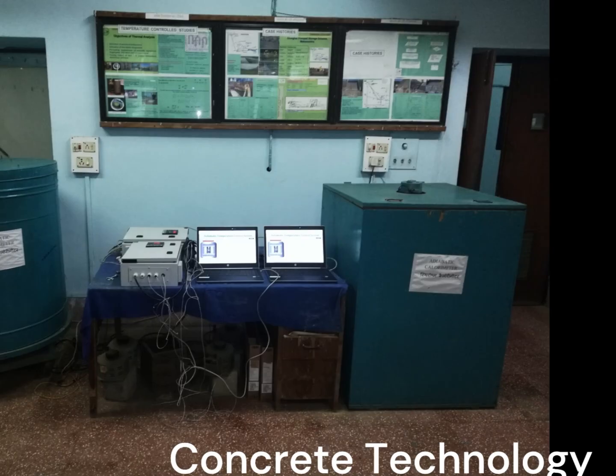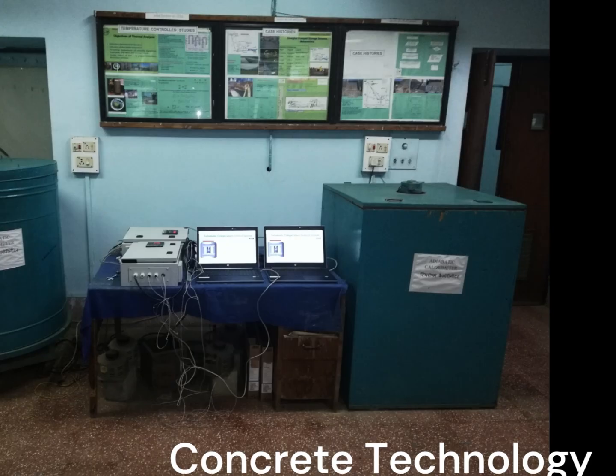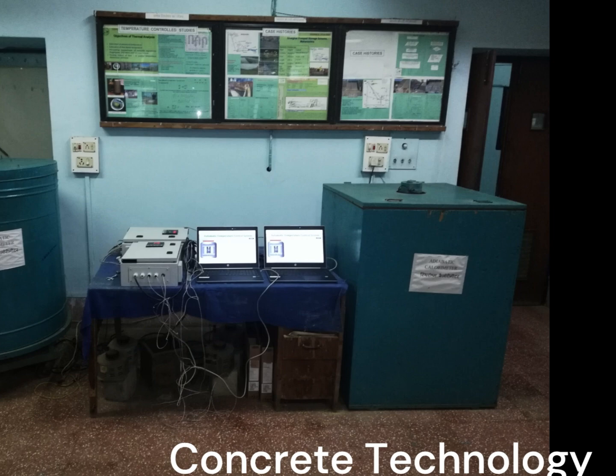7. Adiabatic calorimeter. For measurement of ultimate temperature rise, adiabatic calorimeter is used. 1 cubic feet of freshly mixed design mix concrete sample sealed in a polythene bag has been kept in a plastic container and sealed in a properly insulated wooden box known as adiabatic calorimeter, to arrest escape of the moisture as well as transfer of heat for simulating adiabatic conditions.